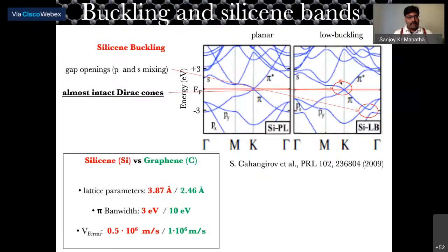And these are the lattice parameters of silicene and graphene. The pi bandwidth in silicene would be around 3 eV. So this is the pi bandwidth; you see the bottom of the pi band is around 3 electron volt. In the case of graphene, it will be at -10. And the Fermi velocity of the bands crossing the Fermi level, in the case of graphene, is 1 × 10⁶ meter per second. But in the case of silicene, we expect to get something around 0.5 × 10⁶ meter per second. Okay.